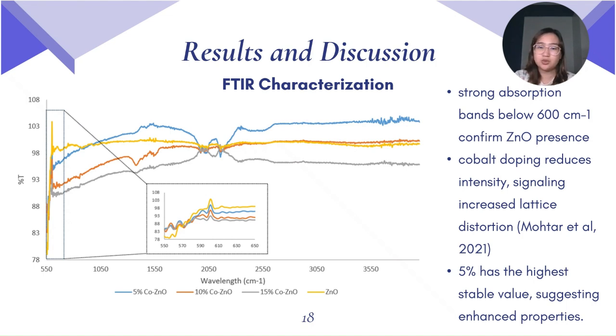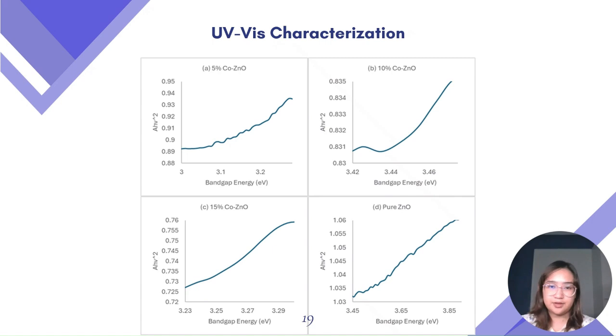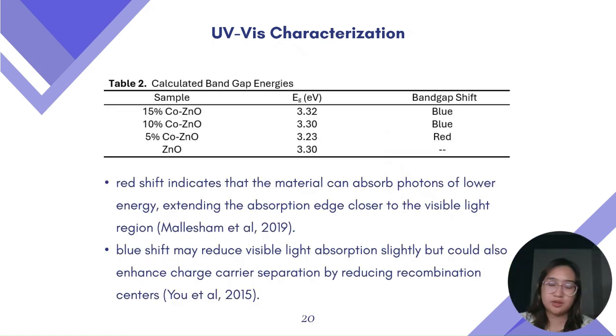The 10% Co-ZnO shows a moderate increase in transmittance but remains below the 5% Co-ZnO sample. Its curve is smoother and the rest of the line has more stability, indicating a more uniform behavior than other samples. The 15% Co-ZnO sample has the lowest transmittance values of the rest, indicating a decline in the structural property with higher cobalt doping. These are the Tauc plots generated from the UV-Vis characterization and the formula mentioned in the methodology. These results in the table are consistent with the typical direct bandgap of zinc oxide reported in the literature, which generally ranges between 3.2 and 3.4 electron volts.